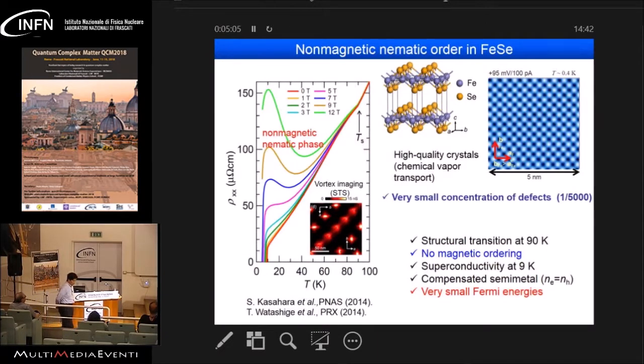In this context, I would like to show you that the iron-based superconductor iron selenium is a key material to investigate the BCS-BEC crossover physics. This material has a very simple structure, with just layers of iron selenium like this. And we can get very high quality single crystals by using the chemical vapor transport technique.